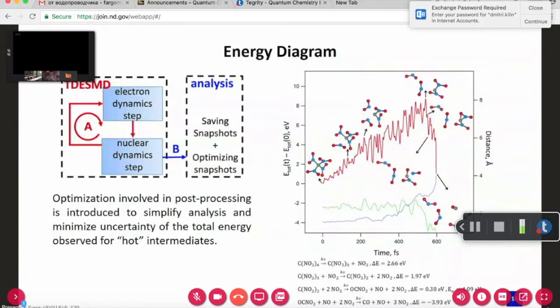And then next, we want to build the energy diagram for the photofragmentation reaction, so that we can get the activation energy for specific chemical reactions. However, in TDESMD trajectories, we get hot intermediates with excessive kinetic energy. So it is impossible to accurately estimate the activation energy based on these hot intermediates. So we have to apply a post-processing technique. What we do is apply single point energy calculations to the intermediates in order to artificially remove the kinetic energy. And after we finish this process, we can get the energy diagram on the right.